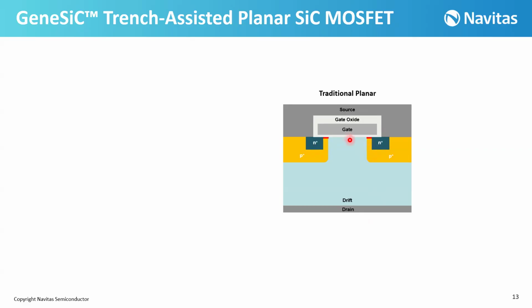However, when we reduce this gate oxide, actually we are making a huge electric field on the oxide, which will cause some reliability issues, and even at higher electric field, it causes breakdown. In order to protect this gate oxide in this traditional planar, normally we are putting a shield. These shields are these P+ implantations under the P-well that can protect the gate oxide by making a good shielding here.